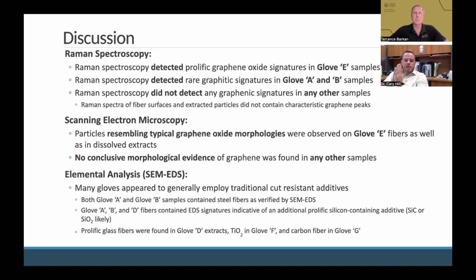So we did not find, through Raman or SEM, any evidence of graphene content in 7 of the gloves. Some showed some graphite, others showed prolific cut resistant additives such as steel fibers, glass fibers, titanium dioxide, silica, or maybe even silicon carbide, depending on the glove sample. So they're using other cut resistant additives. Again, fine to use in conjunction. Just make sure we're being honest.